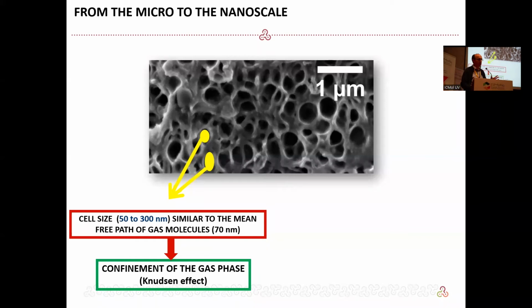And it's very well known from thermodynamics that this changes the way the molecules interact with each other, because they are kind of confined in a small space. This is known as the Knudsen effect. Basically, the interaction between the molecules inside these very tiny cells is much smaller than when the cells are larger. So, for instance, there will be a very low transmission of heat when the molecules are in vibration. So this is one expectation. We will have a Nanoscale effect, and this will translate into a modification of, for instance, the thermal conductivity of the material. This is one of the things that we will now check with experiments.